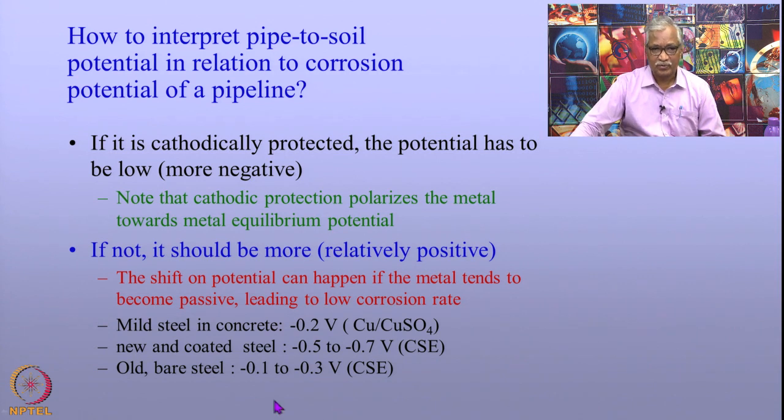You can also see this in real life situations, that the bare metals or new metals exposed to the soil would have relatively more negative potentials, and they suffer more corrosion, as compared to the old metal where the surface is covered with an oxide film, which is a passive film.